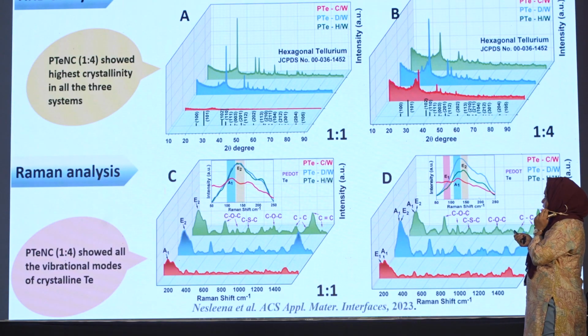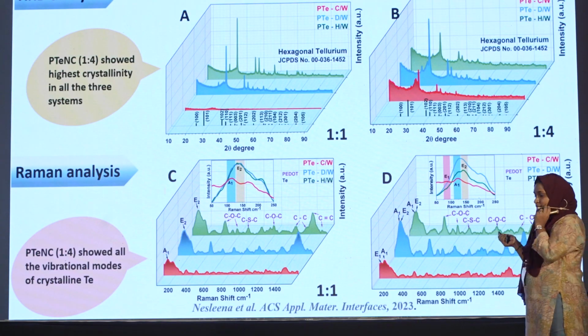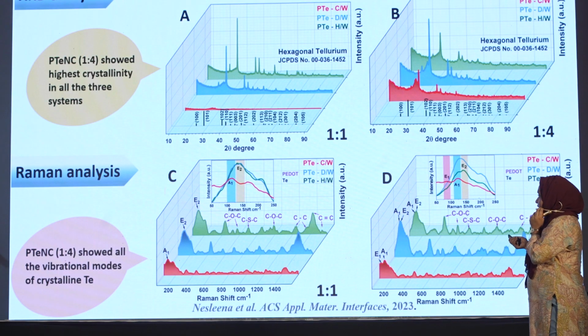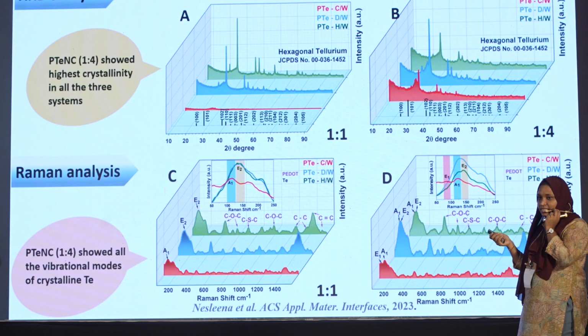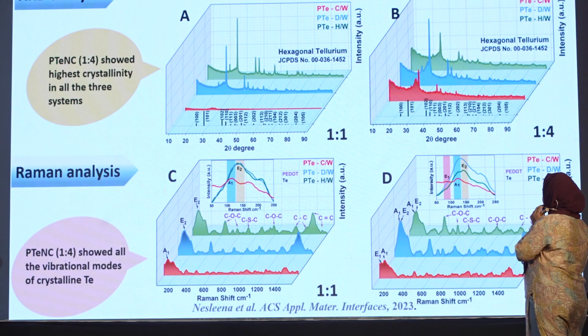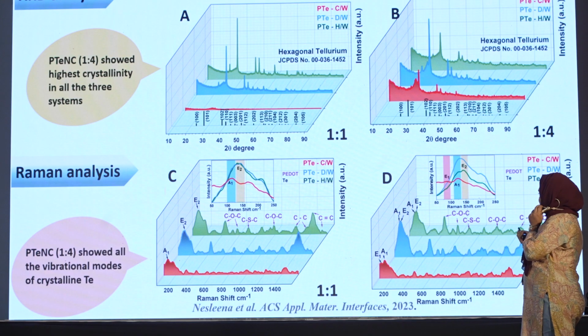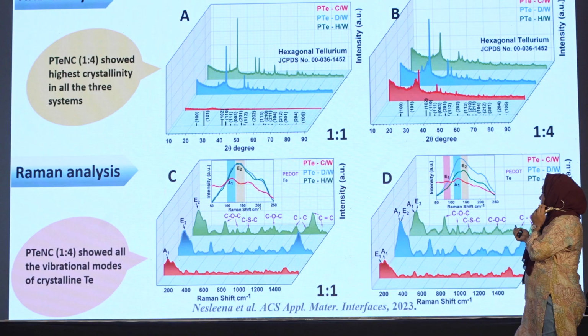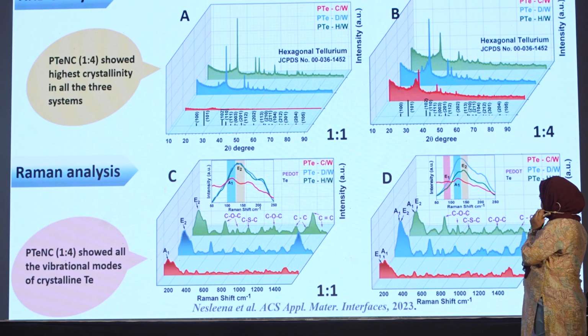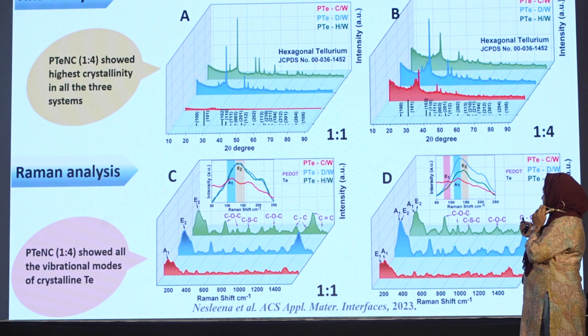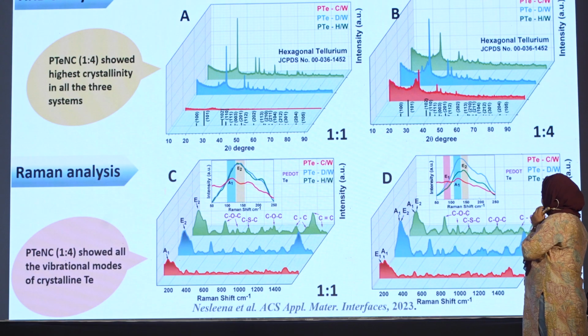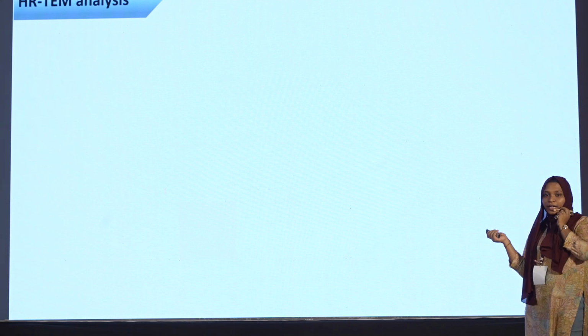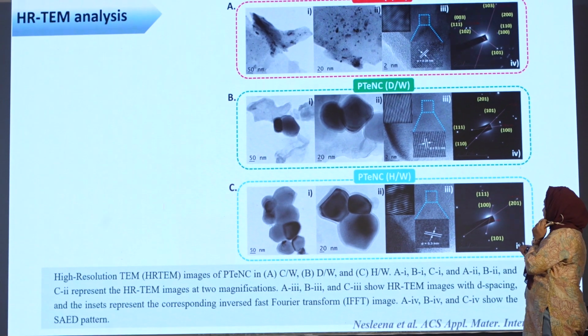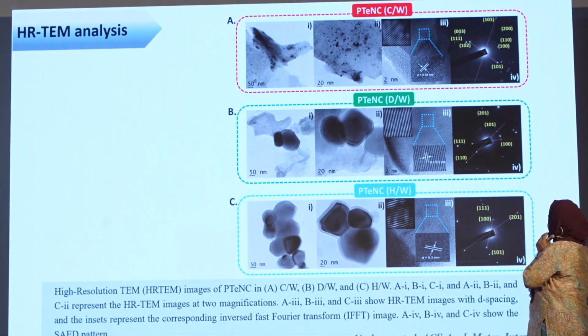We have synthesized PTeNC in two different ratios, 1:1 and 1:4, and from the XRD analysis, crystalline peaks of hexagonal tellurium were observed, and for the Raman analysis, both peaks of PEDOT and tellurium were identified. From both XRD and Raman analysis, the 1:4 ratio was found to be better. So we have chosen that for further in-depth analysis, and for microstructure morphology analysis.